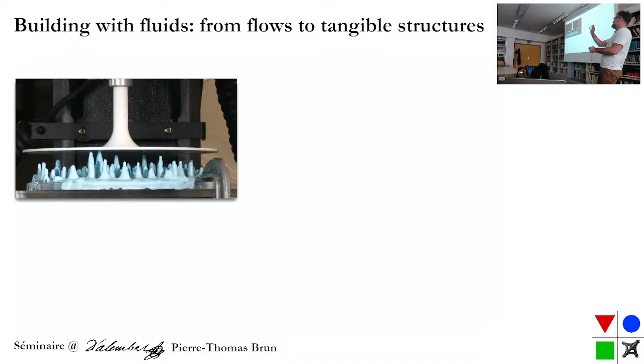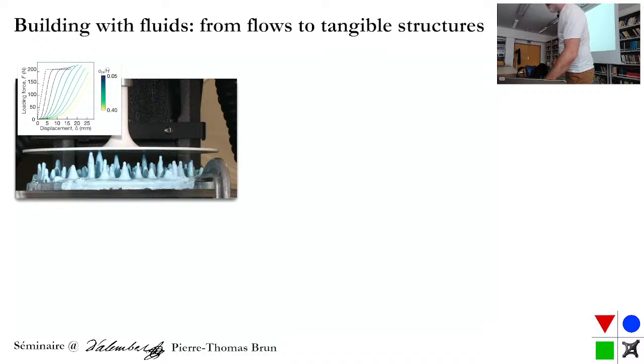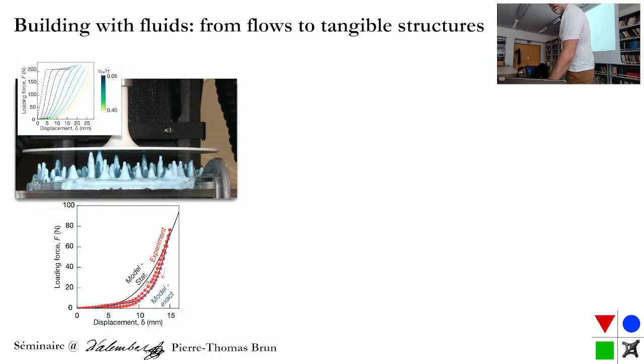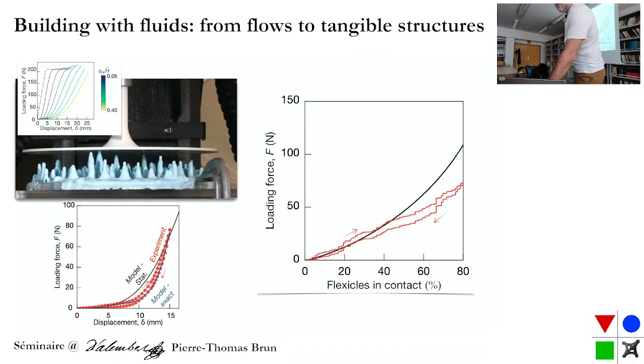So you have a carpet of hairs, and you're going to come and indent them with, in this case, a horizontal plate, sorry. And if you do that, what you see is this. There is the force, and the force is increasing, and it's concave up, right? So it's increasing with the displacement. It's not very surprising. But what's more fun is this.